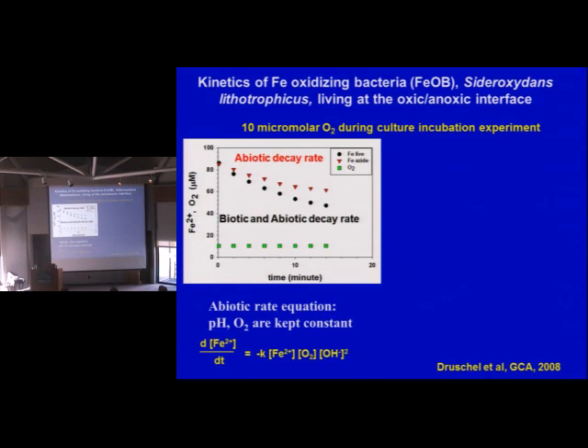So the abiotic rate equation has been known for years by a number of people. This is it. So this is without any kind of autocatalysis with iron oxide surfaces. So you have the rate constant K, which varies with T, times the concentration of iron 2, times the concentration of oxygen, times the hydroxide ion concentration squared. That can be calculated regardless, as long as you know the pH. So you always know what that number should be.